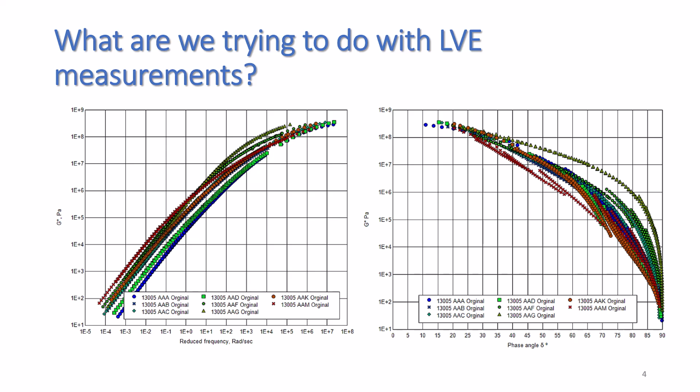And you can see there are different shapes. This one here, you have to have a reference temperature. As I said, this is 25. This one is really independent of reference temperature. And the different curvature for the different binders here really represents the degree of structure in those asphalt binder systems.